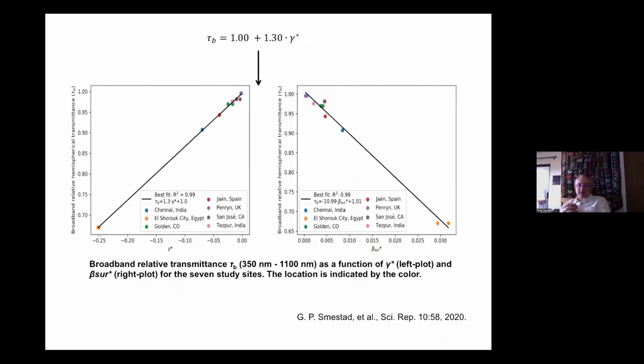Again, coming back to the modified Angstrom equation, we can look here at the y-axis, some of the parameters. Remember, the parameters for the modified Angstrom equation are alpha, beta, and gamma. Well, here's gamma versus the broadband transmission. Broadband, what does it mean, broadband? That means we integrated the average transmission over a wavelength range, I think from 350 to 1100, which is applicable for silicon or PV, if you had it.